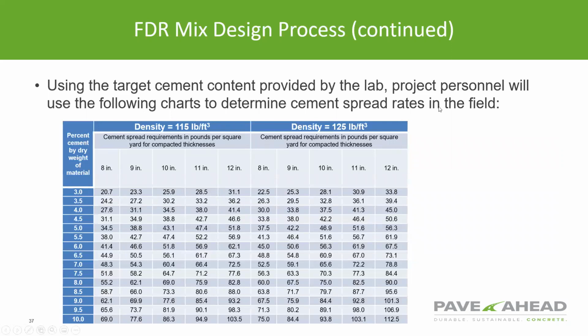We did put together a chart at two different densities, and you can see here we've got two densities of the dry soil. We've got percent cement by dry weight of material over here, and typically you'll see anywhere from 3 to 5% on most FDR projects. There's some states, Idaho, for instance, that actually uses 2%, but they have a process called CRABS, C-R-A-B-S, and